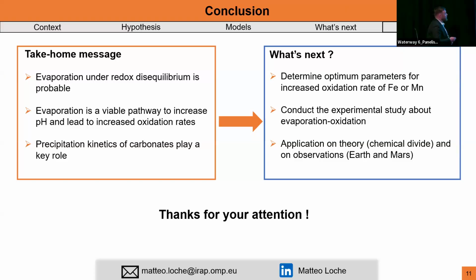And that, as we know it for now, evaporation seems to be a viable way to increase these oxidation speeds and get these oxides that we don't know yet, basically, how to form because of the kinetic limitation. The next steps are to determine this optimum parameter window, so partial pressure of CO2, of oxygen, evaporation rate, and make the evaporation oxidation experiment. So the idea is really to show that the pH is rising, and instead of forming siderites, you're going to form iron oxides, but experimentally.